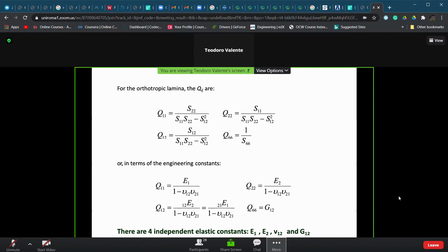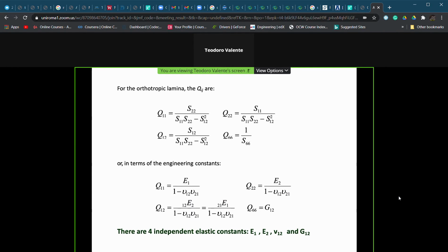And from the previous, that is from the general approach, we can also define the values of the reduced stiffness matrix, which are reported here, or in terms of engineering constants, again the constants estimated by the macromechanical approach, we can write the Q coefficients which populate the matrix as reported here. And as we said already, in this case, with a plane stress condition, we have not 9 as for orthotropic, but 4 independent elastic constants, which are the two Young moduli in the longitudinal and transversal direction, the Poisson ratio, and the shear modulus on the plane 1, 2. And these were exactly the topics of the main estimation allowed by the